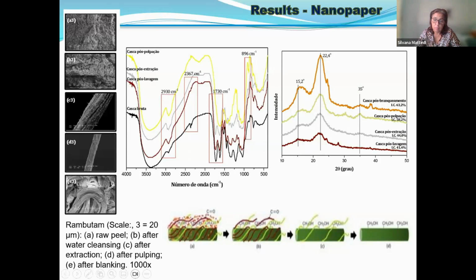Here there are no ionic liquids, but it's interesting to know what really occurs. And this is similar to what we see in that work that I mentioned, where we used the ionic liquid to clean the fiber. We tested sulfuric acid also, but it was not efficient for what we want.